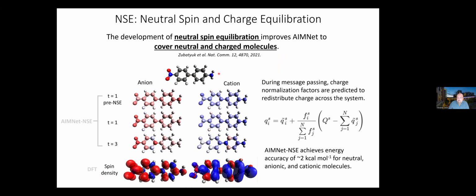Now, if you use just a purely geometric descriptor, that effect cannot be described, and a neural network, not only ours but any purely geometrical descriptor-based neural network, would get you a qualitatively wrong answer, and all charges will have the same phase. With this spin and charge equilibration, through message passing, you update those embeddings inside the neural network, and you can see the formation of the spin wave-like behavior, and overall you can have a proper description of these non-local effects. Again, if you're interested, there's a reference to see how it works.